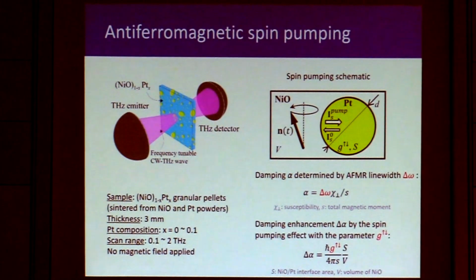So here, the sample we have is a nickel oxide platinum granular pellet of thickness 3 millimeters, and we vary the composition of platinum from 0 to 10%. And we scan the frequency up to 2 terahertz, with no magnetic field applied. Again, the spin pumping picture for the antiferromagnet is very similar to the ferromagnetic case. The damping was determined by the linewidth here by using this equation. And the damping enhancement, delta alpha, turns out to be very similar to the ferromagnetic case, using this parameter, the so-called mixing conductance. S is the nickel oxide platinum interface area, and V is the volume of nickel oxide.